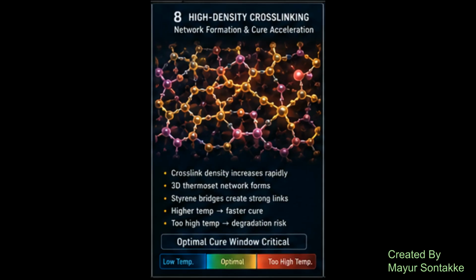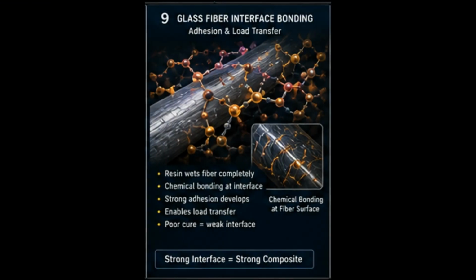A higher temperature leads to a faster cure, but too high a temperature risks degradation. Maintaining an optimal cure window is critical. Strong adhesion at the glass fiber interface is essential for a strong composite. The resin must wet the fiber completely, and chemical bonding must develop at the interface. This strong adhesion enables load transfer. Poor cure results in a weak interface.